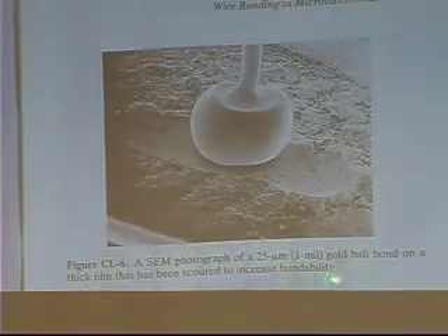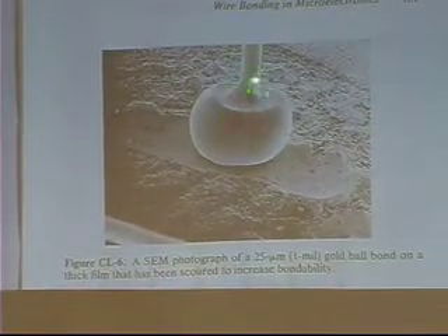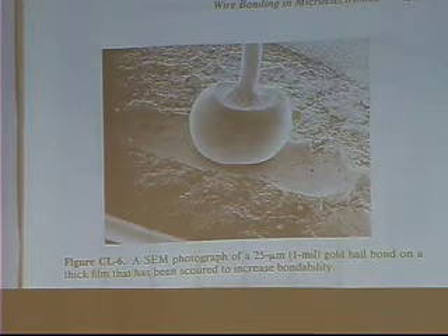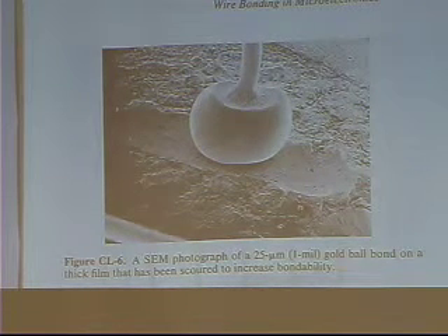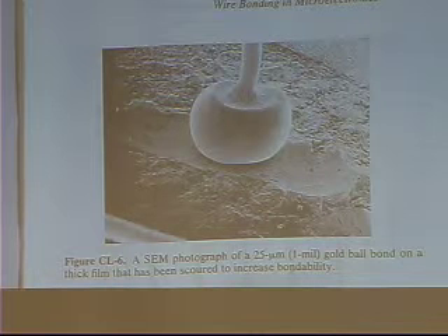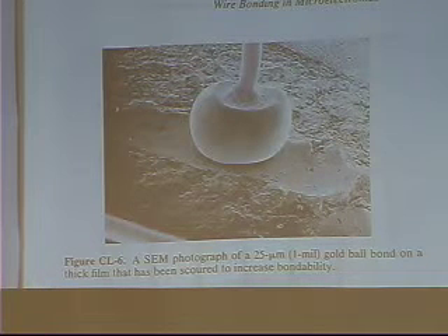This actually is a gold wire, if I remember. A gold ball bond, okay, where they actually used a little arc to melt the surface, and the surface tension caused the ball to form, and then they push the ball into the surface, okay? And I estimated, based on all the semiconductor chips that people make, and this is not the only way we bond, something like 50 trillion of these welds made each year, on that order. So cold welding is important, but it's also important for other things.